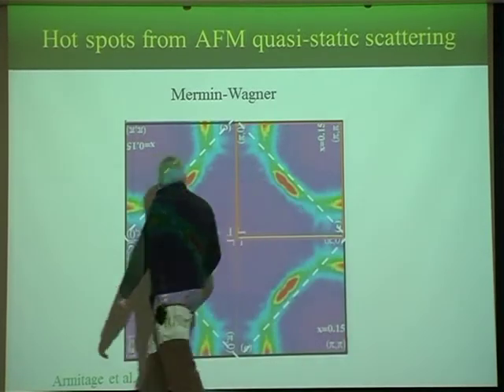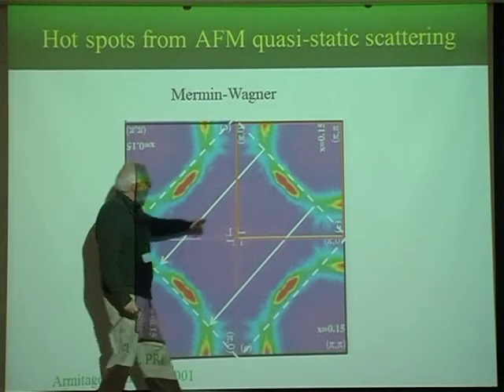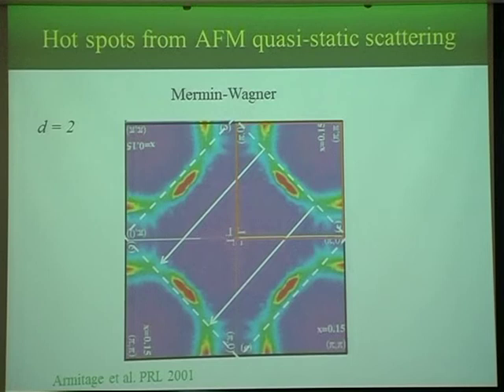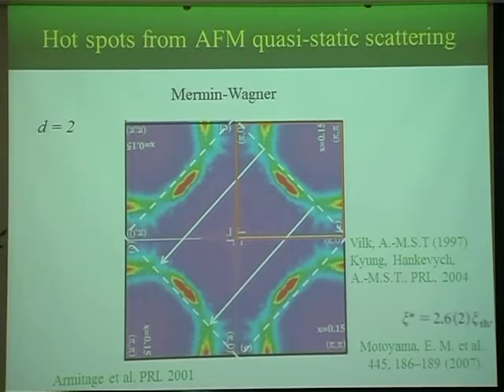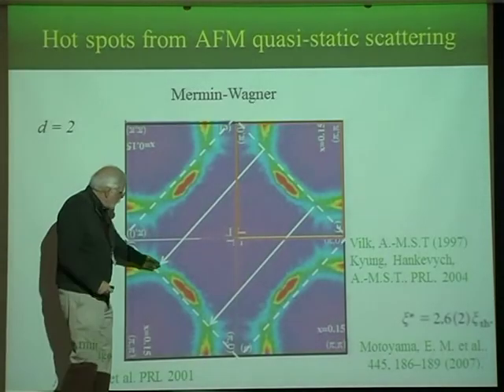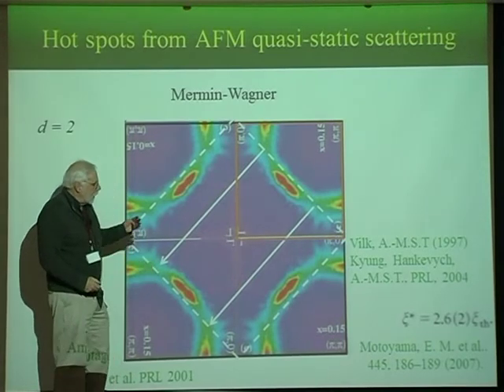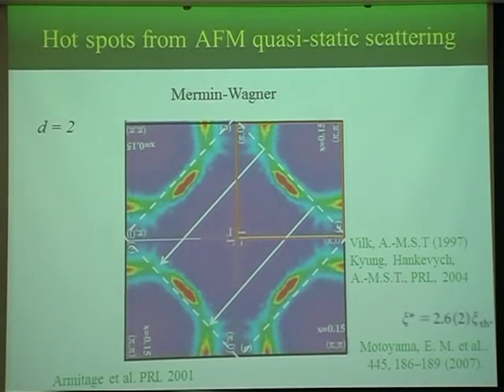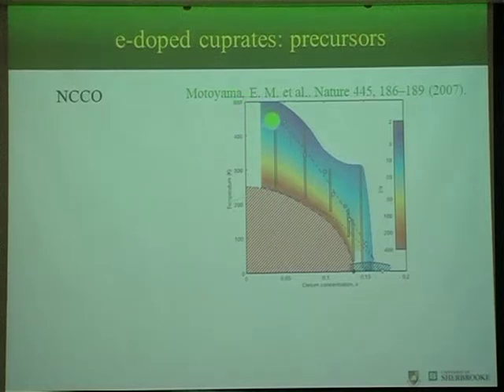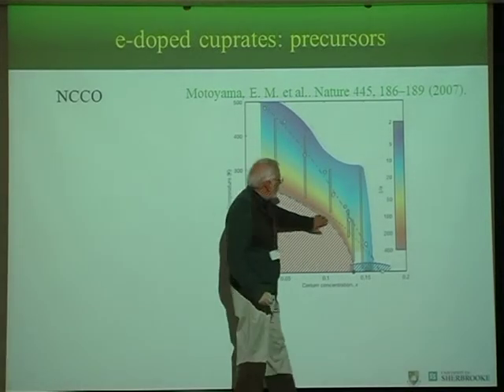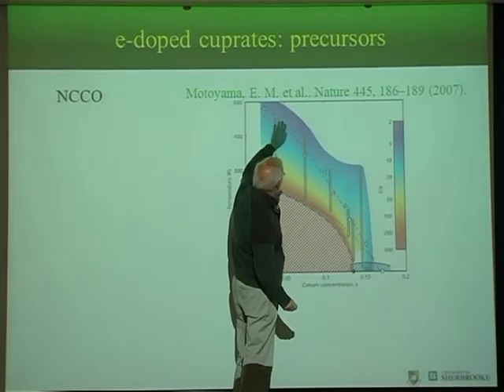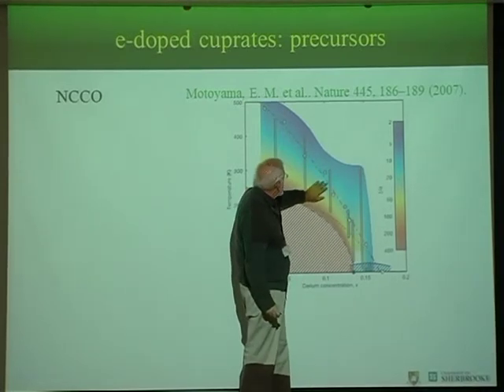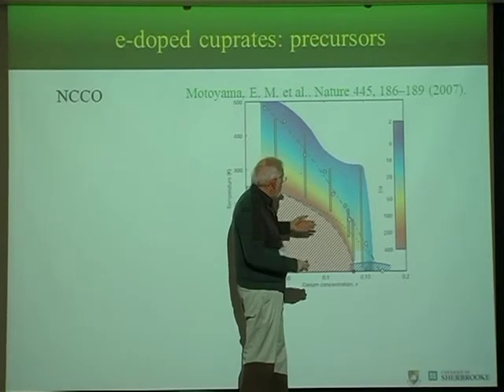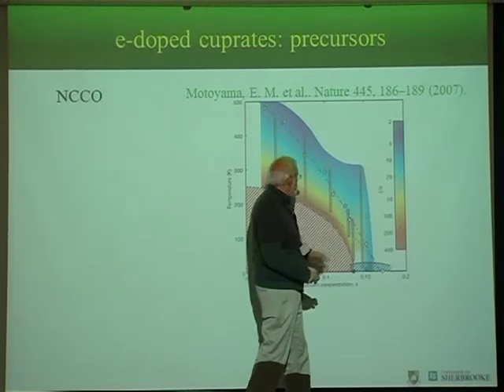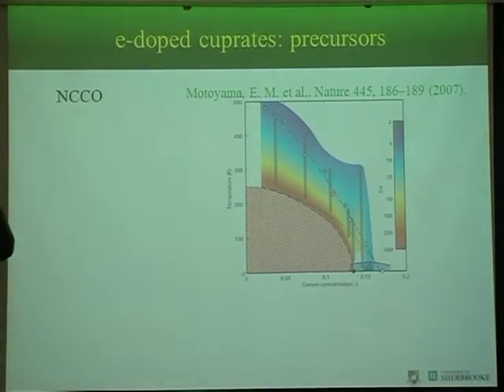So in the electron-doped cuprates, you can understand what is happening as follows. This is the antiferromagnetic wave vector, pi. As a function of temperature, this pseudogap appears when the antiferromagnetic correlation length is of the order of the thermal de Broglie wavelength. And this was verified experimentally. The color code here is the size of the correlation length. Red means like 400 here. Here is 2 or something. And this is where the pseudogap appears. You see that it does not appear when the correlation length is equal to 2 or 3 or anything. It can occur here when it's 50. So the important thing is that it scales like the thermal de Broglie wavelength.